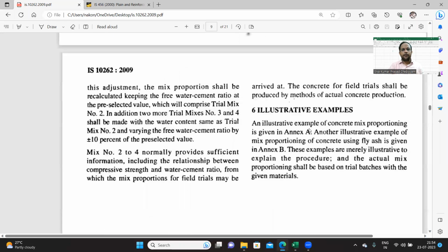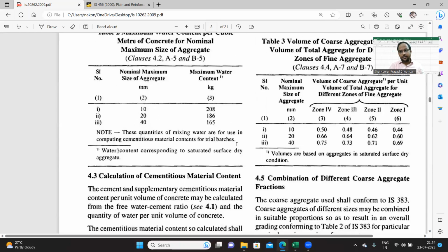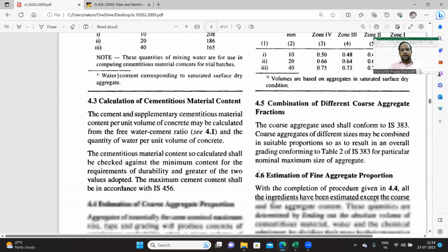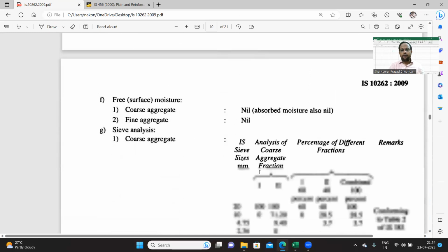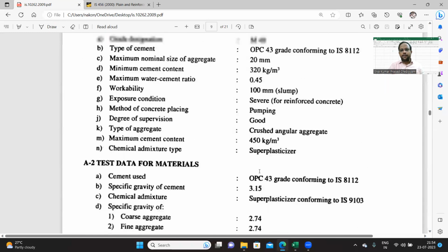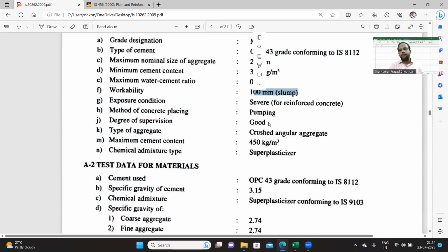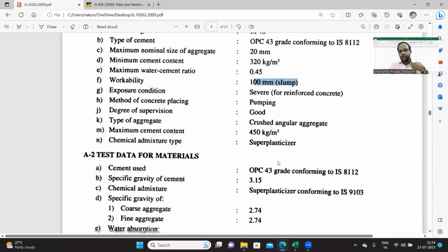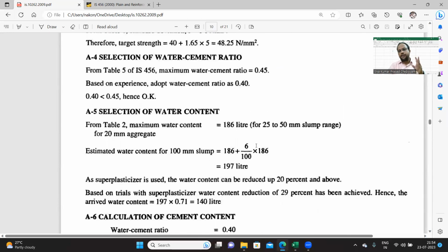So for 25 to 50 mm slump, it is 186 liters. But our slump value is 100. If you see the description of the problem, workability is 100 mm slump. That means in addition to 50, there are 2 more 25s, so we have to enhance the water content by 6%. So that was done.